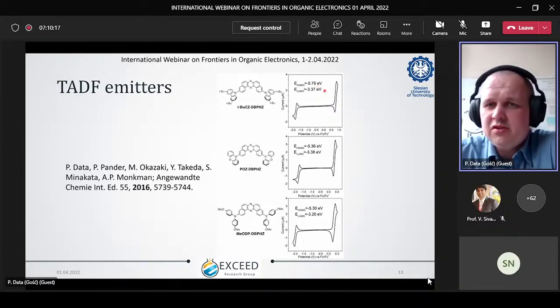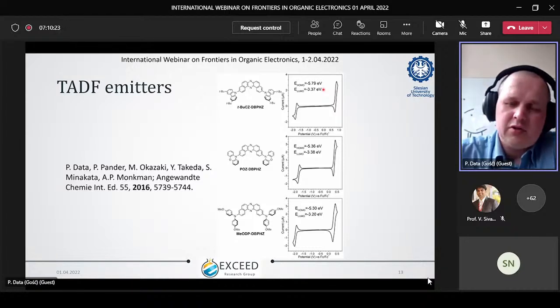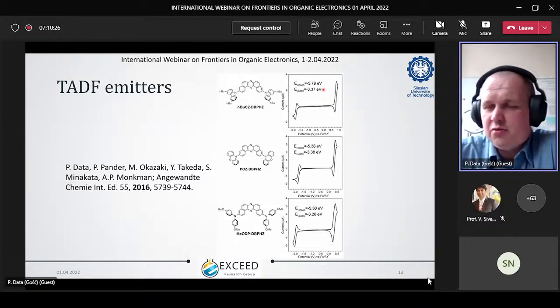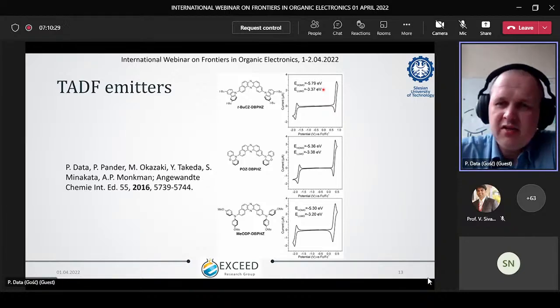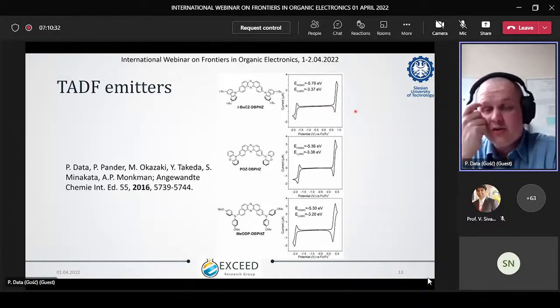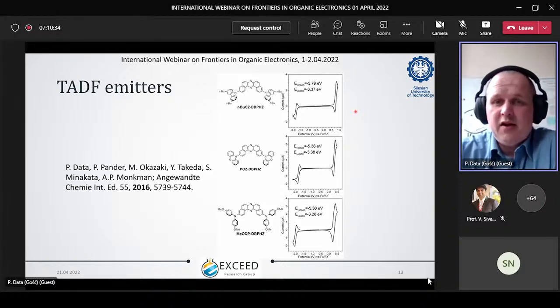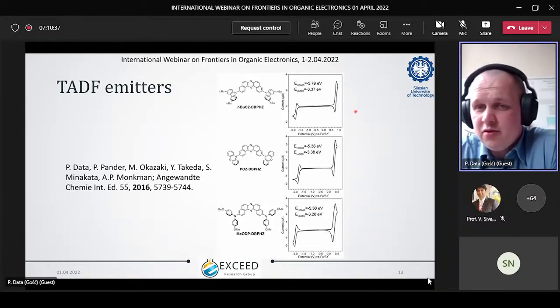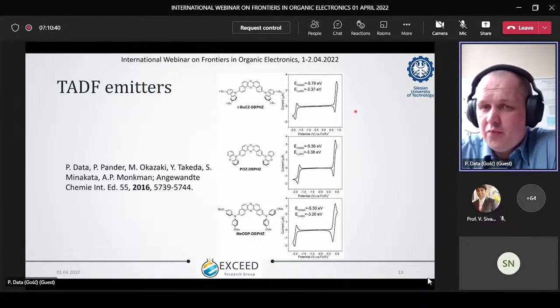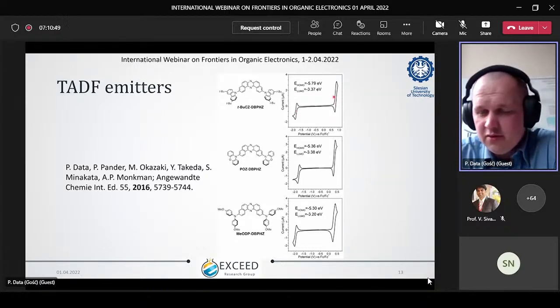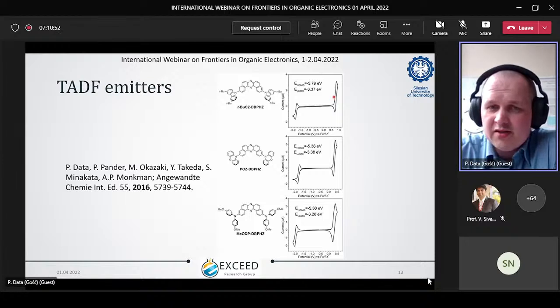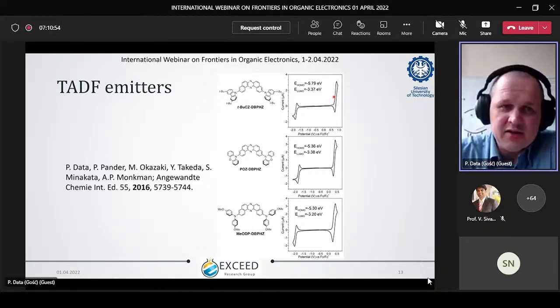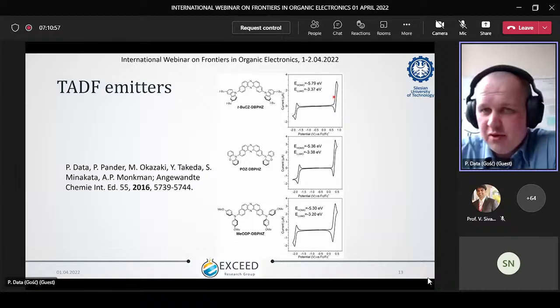And also to know what the HOMO and LUMO levels are, because this factor will tell us what supporting layers, like the hole transporting layer or the electron transporting layers, we can implement in our devices. So those values are important for tailoring the final device. And thanks to that, we also know if our compound is stable, so if our oxidation or the electron doping is a reversible process or not. If it's not reversible, then we need to find out what's going on. So that's why we are starting, for example, in our case, from the electrochemical analysis.